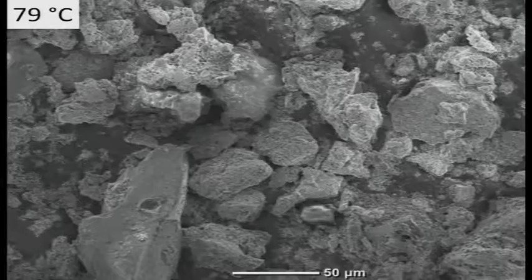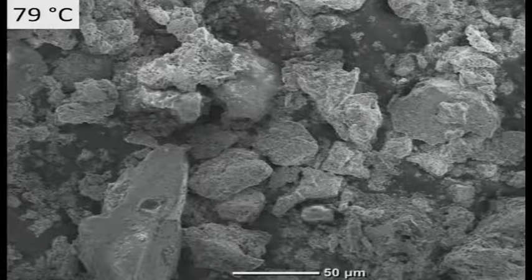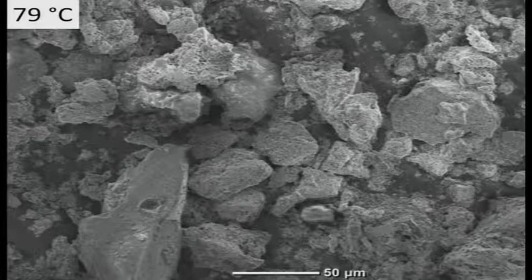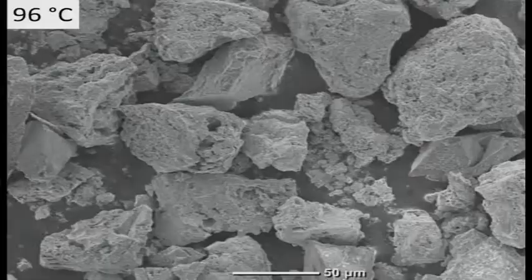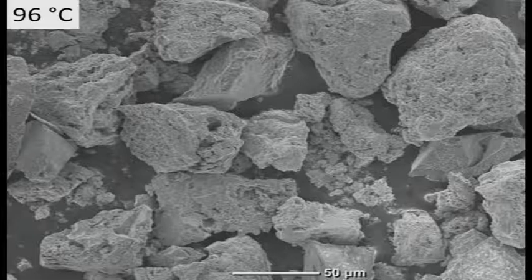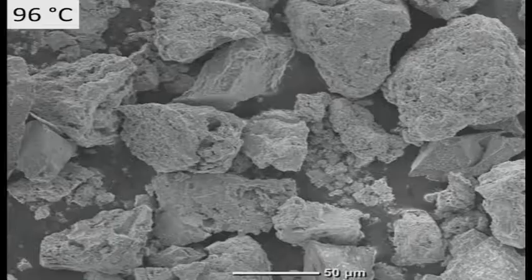After leaching at 79 degrees, there's none of the corroded looking brannerite there. At lower temperatures, the uranium extraction is about 97% at this point, very little of it remaining in the solid phase. So this is just mostly titanium dioxide and a few other things that didn't dissolve. And something similar at 96 degrees. This is mostly titanium dioxide with a few other insoluble materials in there, a small amount of silica, and the lead sulfate I mentioned earlier. Any lead in there would have very quickly formed solid lead sulfate.